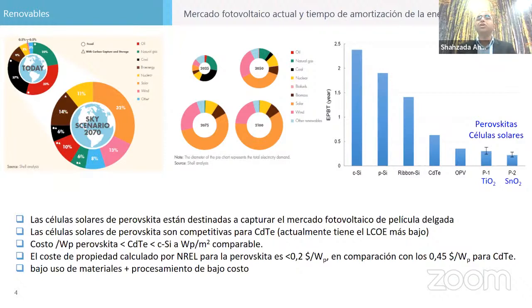Titanium dioxide is a very good photocatalytic and semiconductor material which needs to be annealed at 450 degrees to convert from one phase to another phase. But if you look at tin oxide and other types of N-type material, the energy payback time will be even lower because we don't need high temperature annealing. It is very good to anneal them at 100 degrees centigrade.